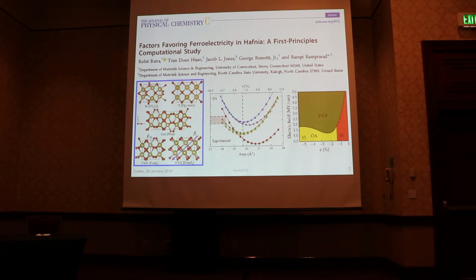And, you know, maybe there's something wrong with DFT, but us theorists would like to understand things a little deeper than that. One of the things that people have thrown out as a possibility, I must say I'm not completely taken by this, is the idea that this polar structure is actually stabilized by electric fields, but they're reasonably high electric fields, like 200 megavolts per meter. I mean, it's possible. But anyway, if you drive it with an electric field, you can make this polar structure stable. And so this is showing monoclinic, the nonpolar orthorhombic structure, and then the polar orthorhombic structure as a function of strain and electric field.